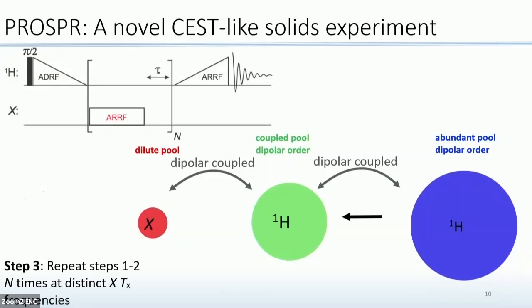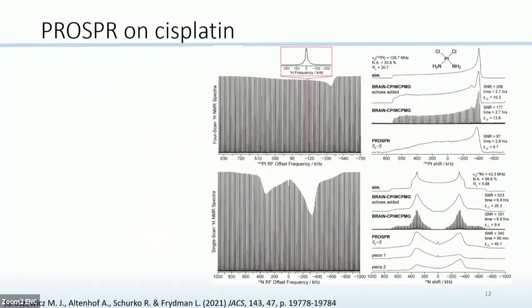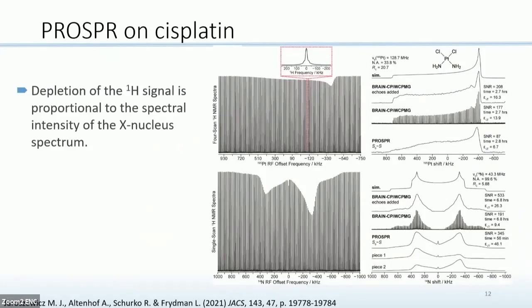So then we basically return to the same point, and we can repeat it n times. Following that, we perform a remagnetization pulse, and then we read out what was left from the dipolar order. So we can see, according to the sequence, that we would benefit from long T1Ds. The longer our T1D, the more we can repeat it, and the more we can deplete the dipolar order on the protons.